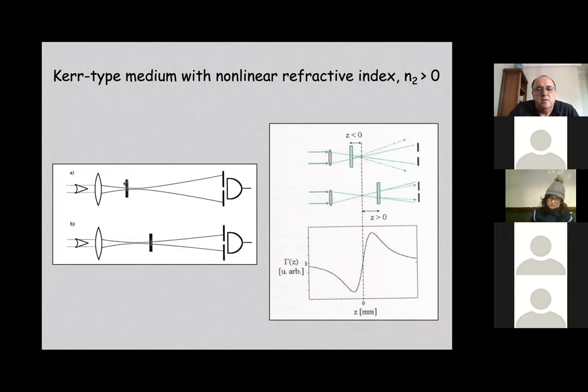If your sample is a nonlinear optical sample or a Kerr type medium, what happens is that if you are before the focus, we have a divergence of the field here. So less energy will go through this pinhole, this iris. When you cross the focus point, it will focalize the beam, so you have more energy in this iris. This is the typical normalized transmission as a function of the Z position of the sample. It's named Z-scan because we define the horizontal direction as the Z-axis. When we move the sample across the focal point along the Z-axis, we have this type of behavior of the intensity measured after the iris. So this is the typical result.